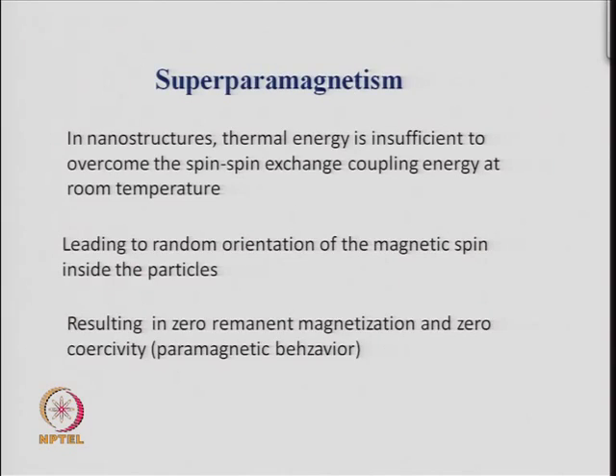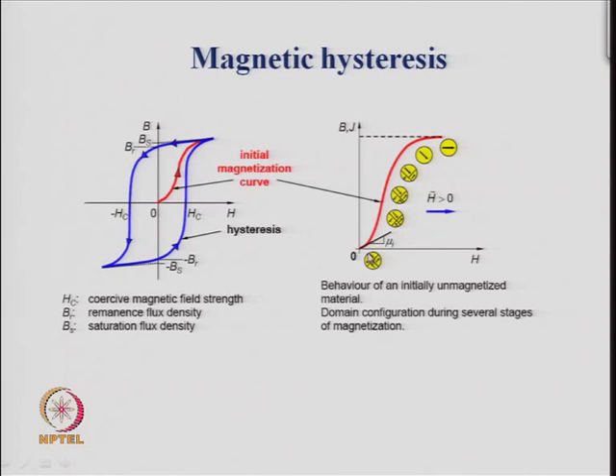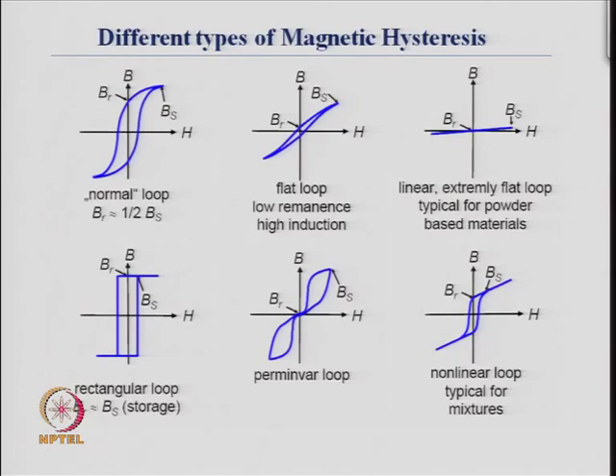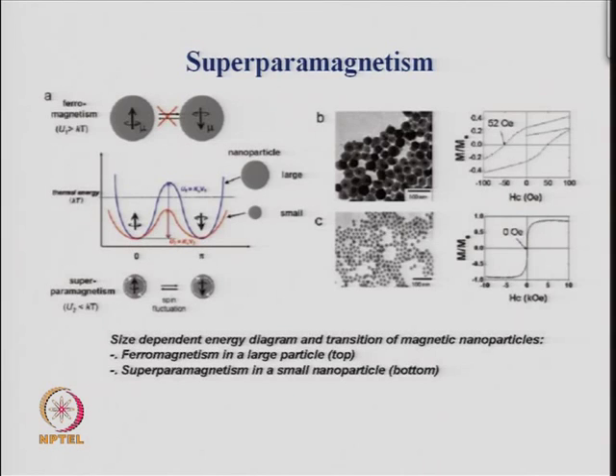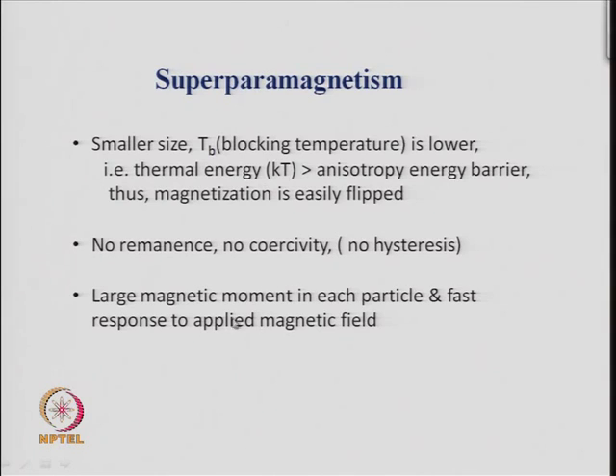So, if you see the plot here, which we mentioned initially, the length of the arrows may be taken as the magnitude of the moment. Now, these are very small. As you are changing the field, you see this arrow is growing and becoming larger and larger. Here the length of the arrow is much higher, that means the magnitude of the magnetic vector is higher, and that will always be found in super paramagnets, where you will have a large magnetic moment in each particle, and also a fast response to the applied field.